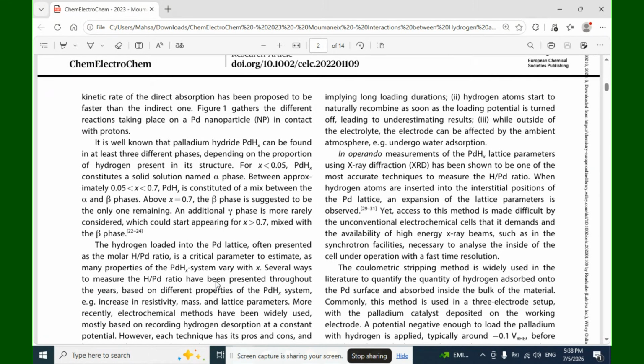Another approach is operando measurement of the PdH_x lattice parameters using X-ray diffraction. XRD has been shown to be one of the most accurate techniques to measure the hydrogen palladium ratio when hydrogen atoms are inserted into the interstitial positions of the palladium lattice and expansion of the lattice parameters is observed. Yet, access to this method is made difficult by the unconventional electrochemical cells that it demands and the availability of high energy X-ray beams such as in synchrotron facilities,